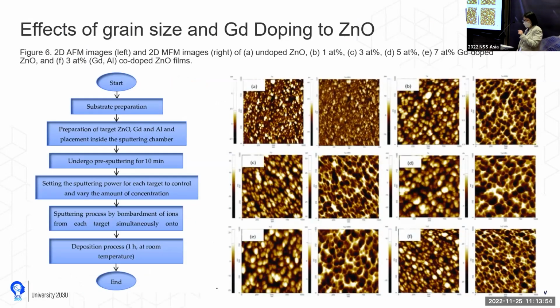Right, so this is another work done in our lab, which is doping gadolinium into zinc oxide for the application of spintronics. Yeah, so as the doping percentage of gadolinium increases, the grain size increases, and also the MFM, magnetic force microscopy, indicates that the force distribution is also around the grain size. So it depends on the grain size of the gadolinium doped into the zinc oxide.